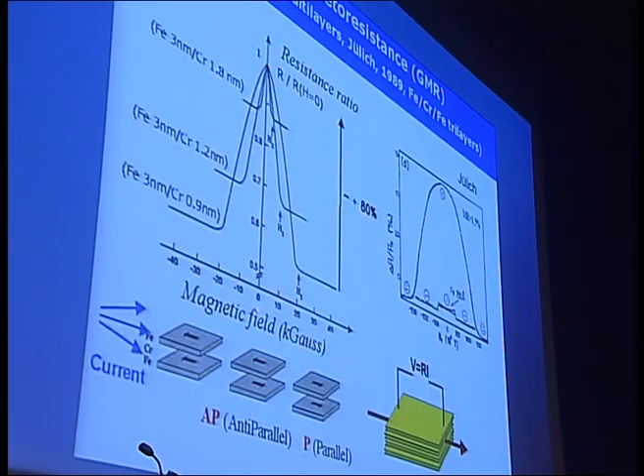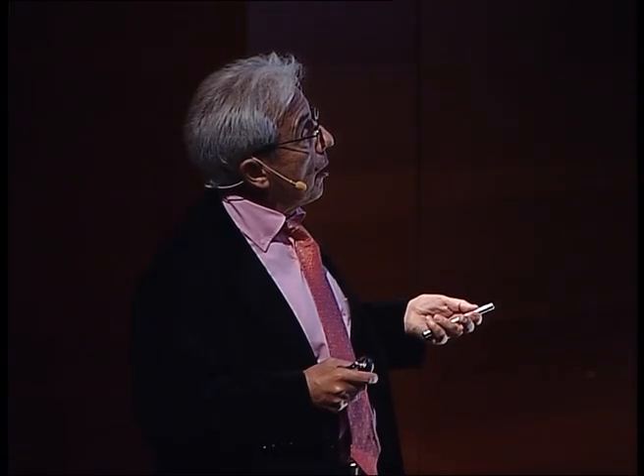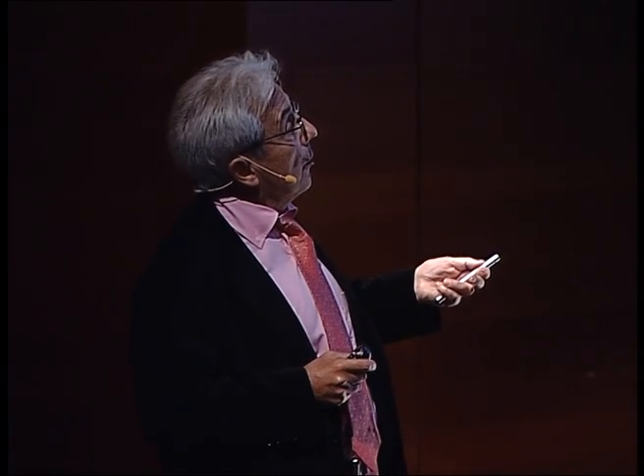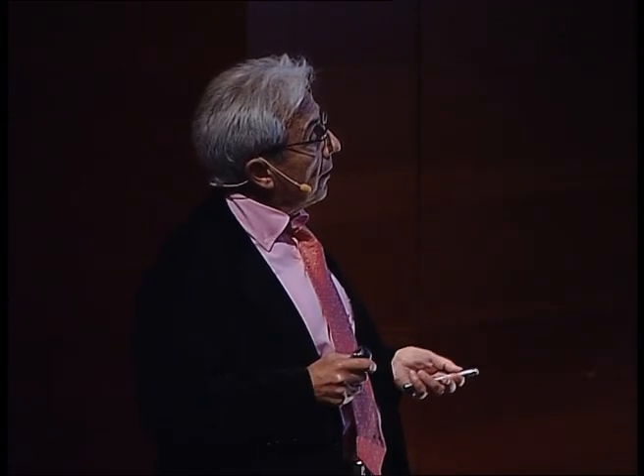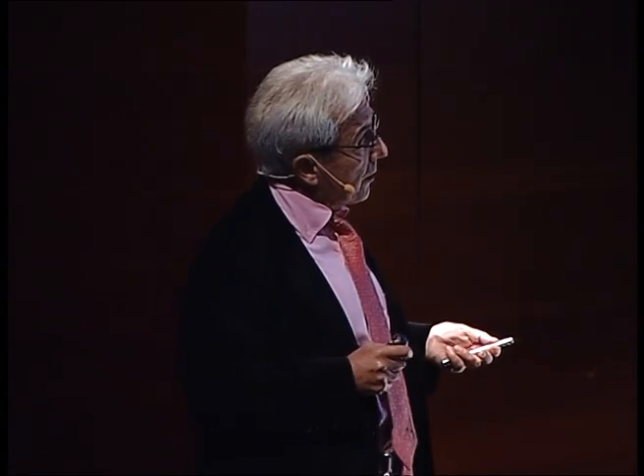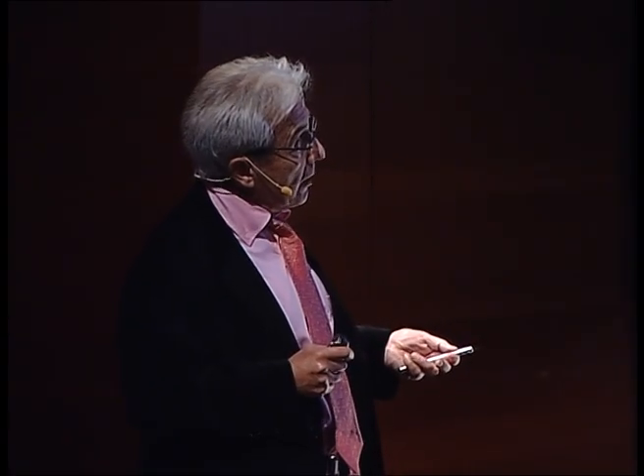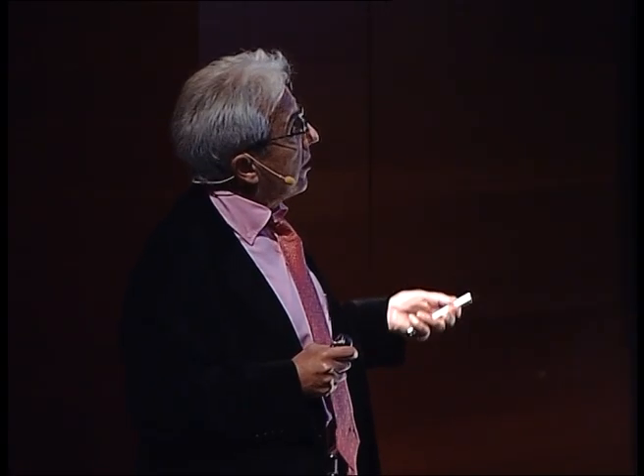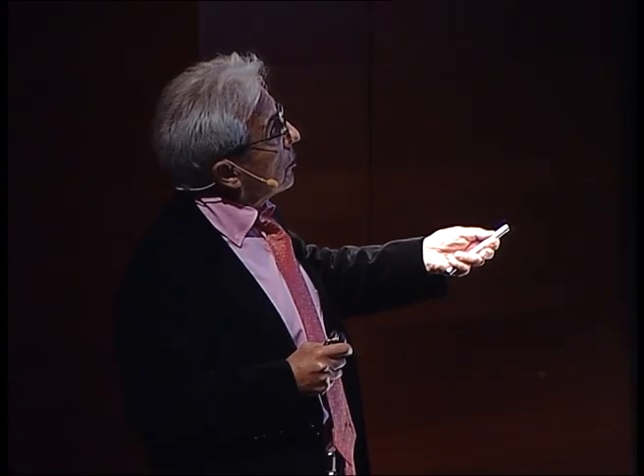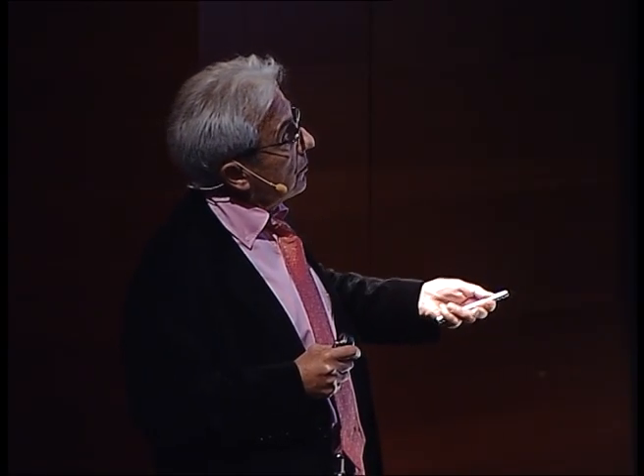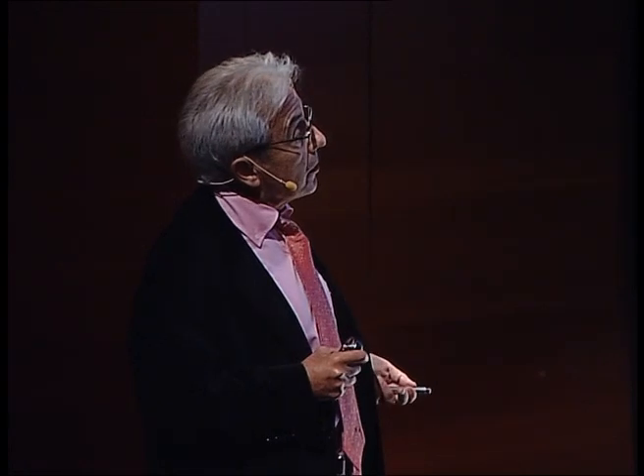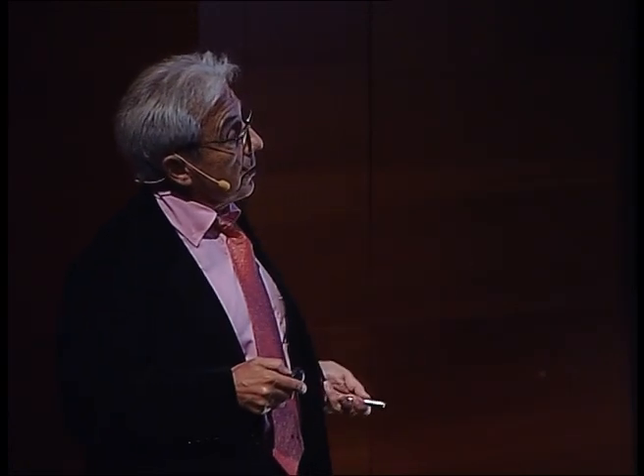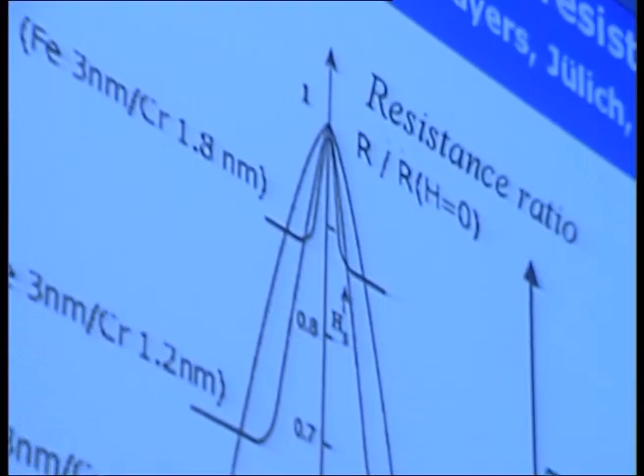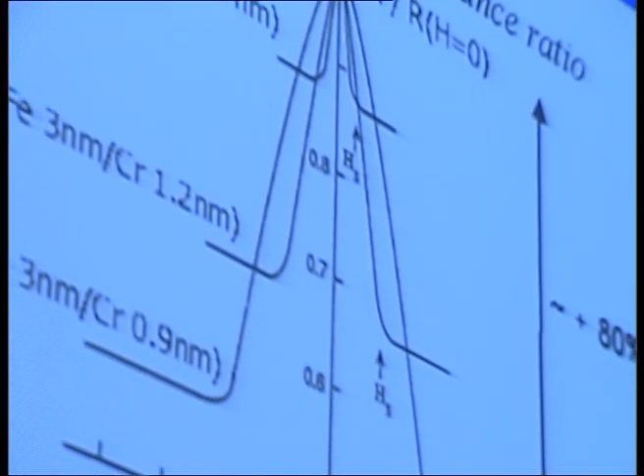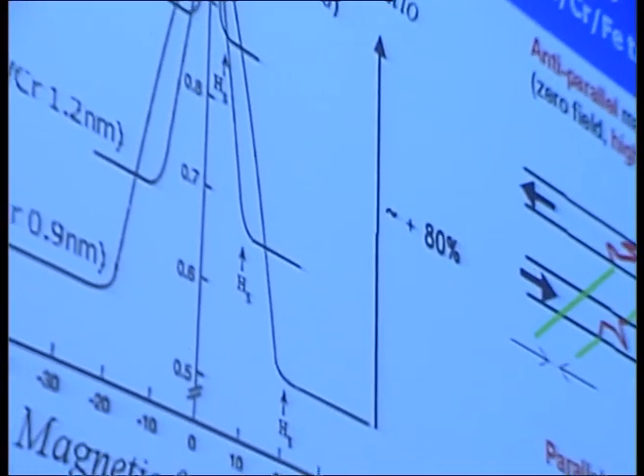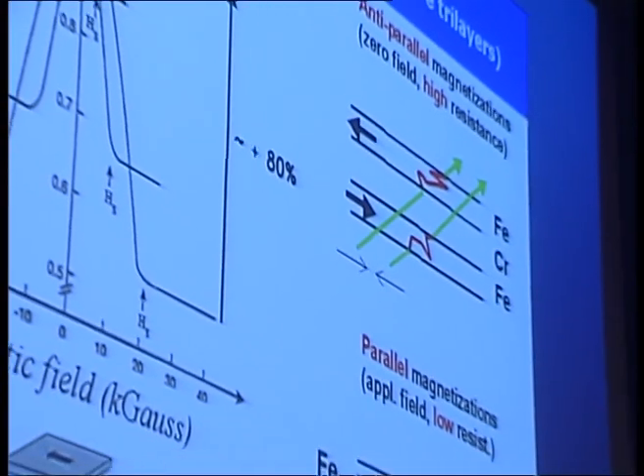So this is a typical initial GMR curve we published in '88. As a function of the field, the field destabilizes the anti-parallel configuration and aligns the magnetization of all the iron layers, and the magnetoresistance has a corresponding drop, 80% of the resistance of the multilayer. And the same results in Germany. So the mechanism is exactly what I can repeat from what I said for the ternary alloys.